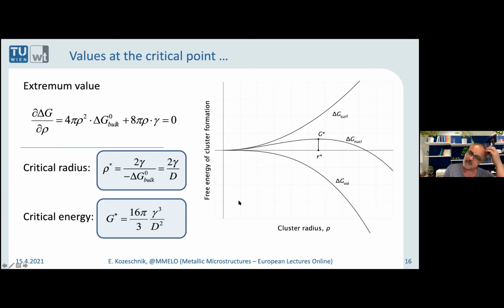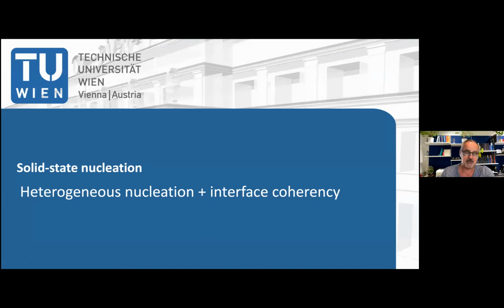And the barrier contains more or less two parts. The one is the interfacial energy cubed and the volume free energy change, or let's say the driving force for second phase formation squared. Yeah, so these two quantities are more or less the ones that we are interested in for the further study, because one of my favorite things is always predict something and do not simply fit to something. Yeah? So my ambition has been to predict nucleation of new phases instead of just fitting quantities like interface energy is a typical quantity. I don't want to fit that, I want to predict it. So this is classical nucleation theory. The idea is to define this nucleation barrier from the volume and the surface contributions.